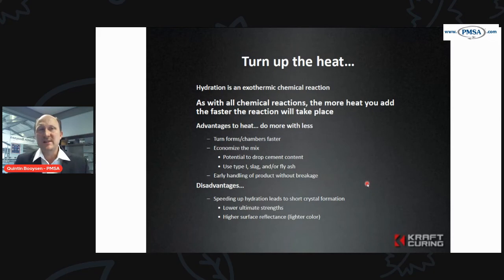There are also disadvantages if you speed up the hydration too fast by adding too much heat, too much moisture right in the beginning of your curing process, especially the heat. You end up with short crystal formation. Earlier we spoke of those crystal fingers that come together. If we heat it too fast and allow too much heat, you get a quick strength, but you don't really get the best possible concrete. So it's a balance between strength gain and ultimate durability of your concrete.